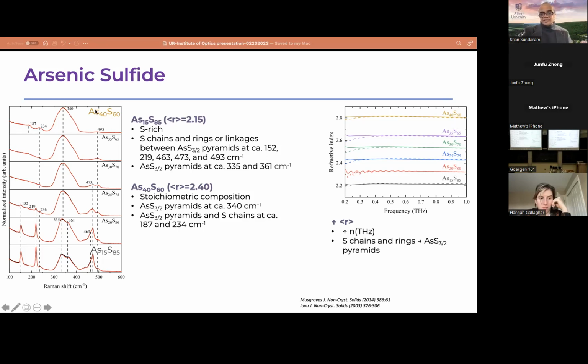By looking at these various signatures, I can recognize the arsenic S3 pyramids at 152, 219, at various bands I'm seeing. And whenever I'm looking at the sulfur-rich side of arsenic sulfide, I'm seeing more chains and rings and linkages, while on the arsenic-rich side of the composition, I'm seeing close to stoichiometric ranges and predominantly pyramidal structures. So you can clearly see we can use this spectroscopy technique to exactly recognize what the various structural components present in the glass are, and then we can look at the terahertz properties of these glasses.